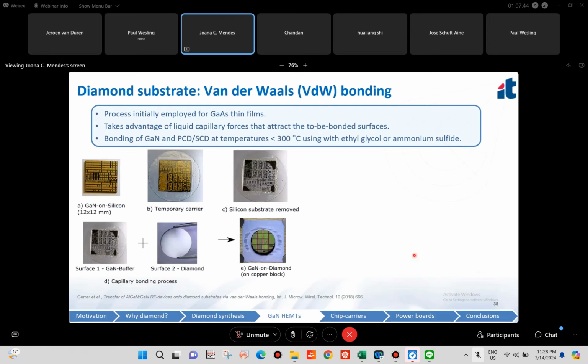You see here the flow of a particular process, GaN on silicon, attached to a temporary carrier after removal of the silicon substrate, and then the two surfaces to be bonded, the GaN and the diamond, and then the whole set mounted on a copper block.